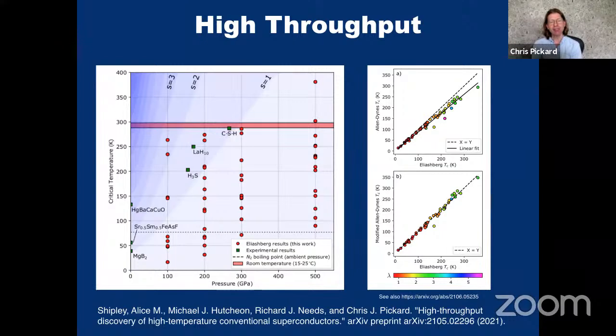Strikingly, we found that the maximum TCs that we were finding weren't decreasing too much as we lowered the pressure until we reached 10 GPa and we didn't find any. But it seemed like we probably should have done 50 GPa, because we might still have kept the high TCs at those pressures. But it's certainly encouraging that these high TCs are not just the domain of these very high pressures. The other slight side effect was that given that we'd got all this data, we were able to reparameterize the Allen-Dynes equation and find a more accurate way of predicting what the TC is without doing the full Eliashberg calculations. This has actually been done even in more detail by Richard Hennig and his group, using much more advanced machine learning methods than just linear approaches, but I think with quite similar results.